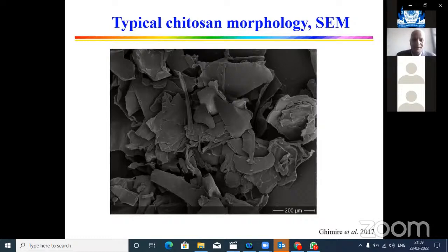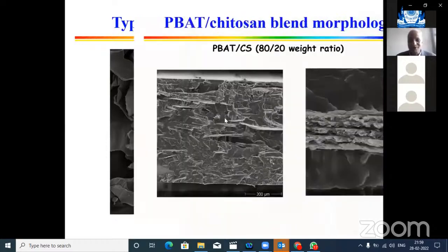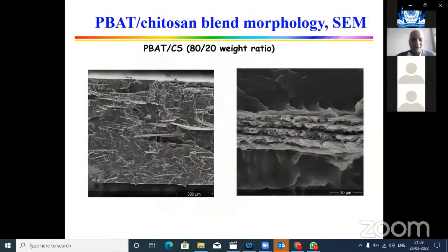When we take it and mix-process with the matrix material, we come to the structures shown here. On the left side, we have the lower magnification scanning electron micrographs, and on the right side, the high magnification. You can see that at high magnification, the chitosan flakes have been embedded with good bonding with the matrix polymer, forming several layers of chitosan that are several hundred nanometers thick and several microns long.